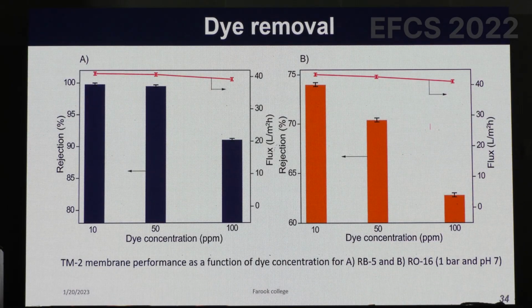And the dye removal efficiency, in one of the dyes, was almost 98 to 99%, whereas in the other one it is about 74 to 75%. It's mainly because of the size of these materials, the dye molecules, as well as what type of pH is maintained during the purification.